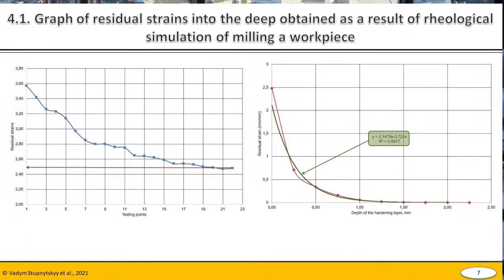The methods of determining the depth of residual stress are similar, but the test points for measuring deformations are not located along the length of the processed surface, but into the depth. It is obvious that the modeling of the depth pattern should also be done in the zone of thermal stabilization of the machined surface. The simulation results are shown here. Next slide, please.